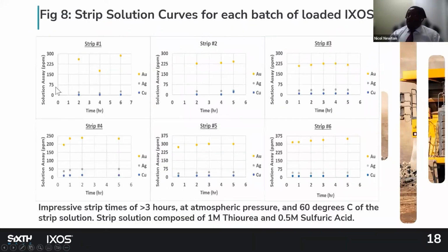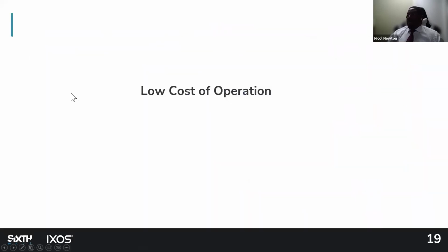This is some of the strip results that we had. Very impressive strip times. We're stripping all the gold in less than 3 hours, and at atmospheric pressure, 60 degrees C, and the strip solution used was 1 molar thiourea and 0.5 molar sulfuric acid.